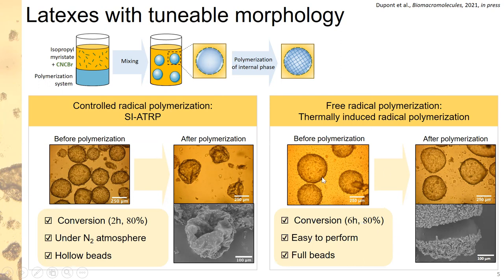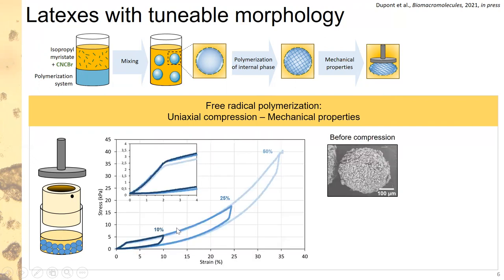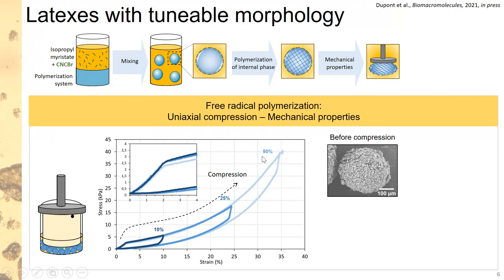We continued with this system to assess the mechanical properties of the objects. To study the mechanical properties, we used uniaxial compression: the sample was placed inside a vial and compressed with a rheometer using a porous disk that allows diffusion of only the liquid phase. The graph shows stress in kilopascals as a function of strain. We imposed different deformations from 10 to 50%, studying both compression and relaxation, and observed a clear linear elastic domain.